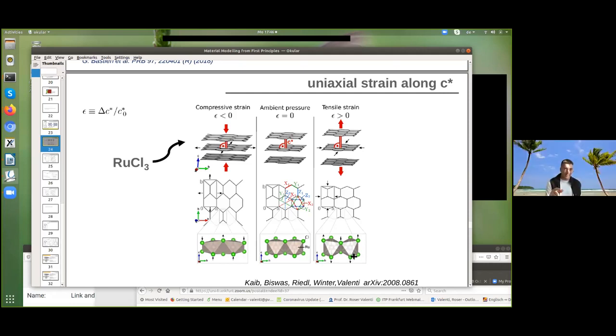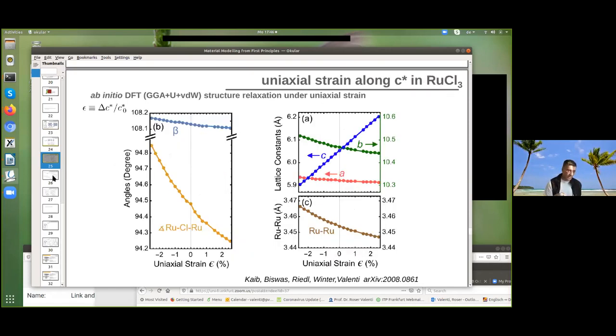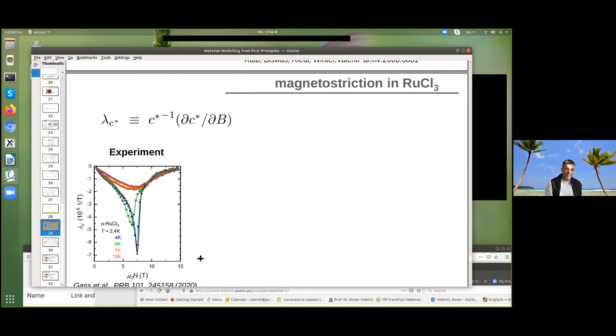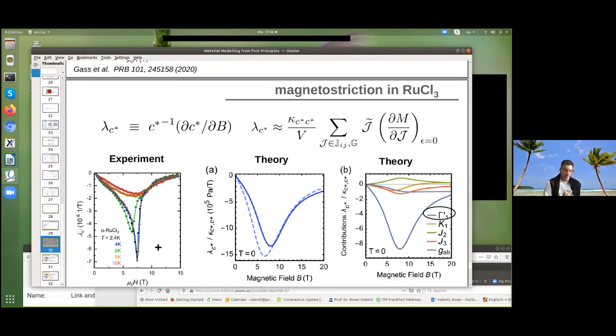On the next slide, you had the phase transition in experiments. I think the second to the last. Yeah, this one. So clearly, as you pointed out, the data shows effects which are associated with the phase transition, with the ordering. Does your theory also contain the ordering to some magnetic state? Yes, of course. These simulations here are of the ordered state, considering the model, which itself has a phase transition at 6 Tesla. So the model contains this order and the disappearance of the order at 6 Tesla.